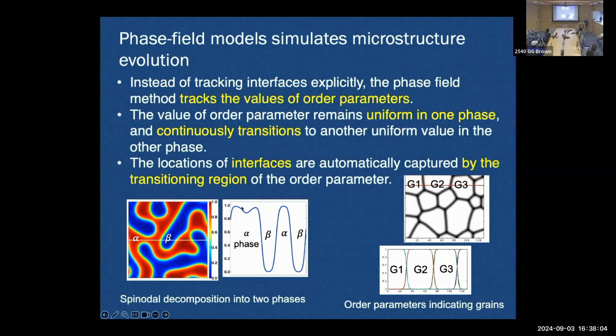And then you have those phases developing. It's not quite 1 over here, but it's going to be eventually. And then there's a beta phase region, alpha phase region, beta phase region, etc. This green area is the interface in this case. So instead of tracking interfaces explicitly, the phase field method tracks the value of this order parameter, in this case the scaled concentration. The value of the order parameter is uniform in one phase. Once it phase separates completely, you're going to see 1 over here, and then it continuously transitions to another uniform value in the other phase. The location of interfaces is automatically noted by the region where the order parameter changes fast.